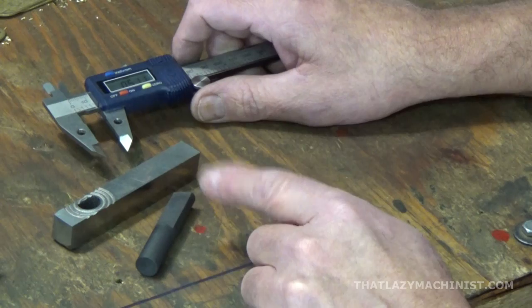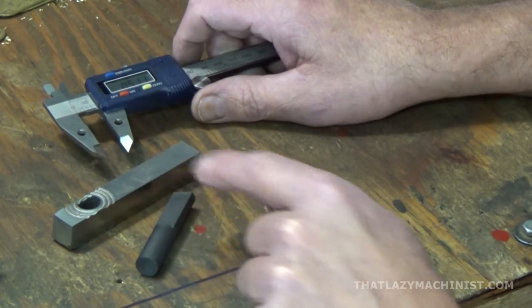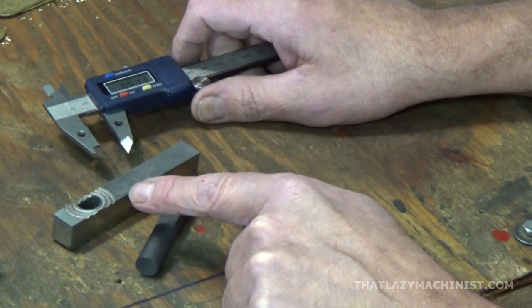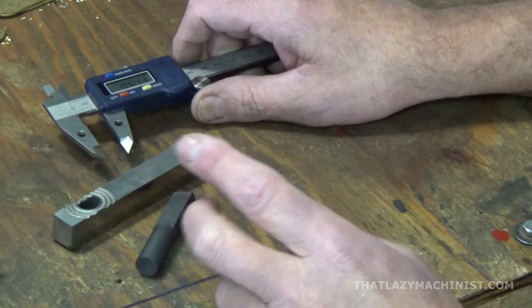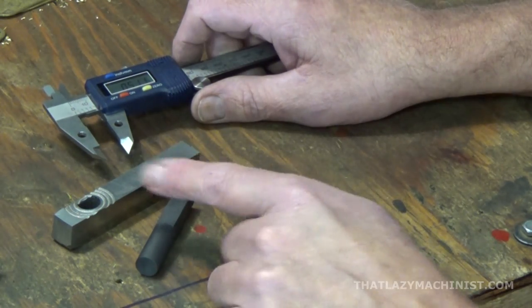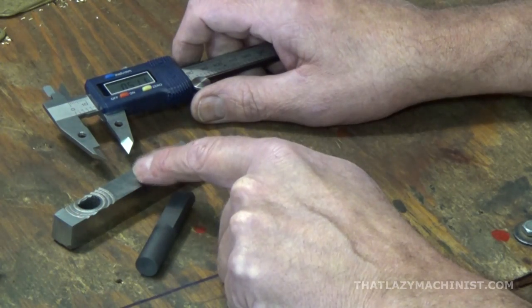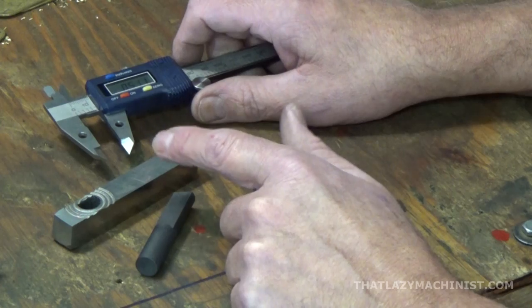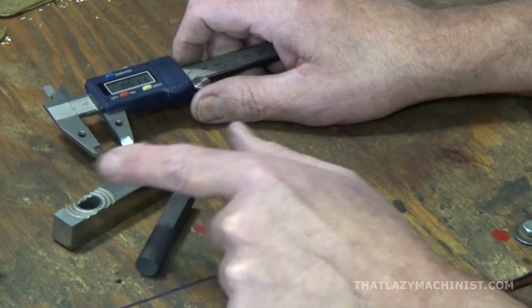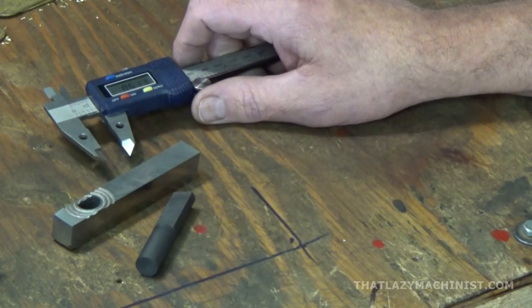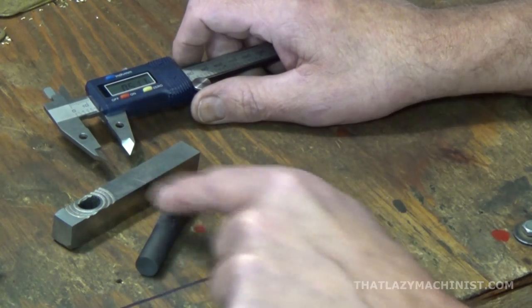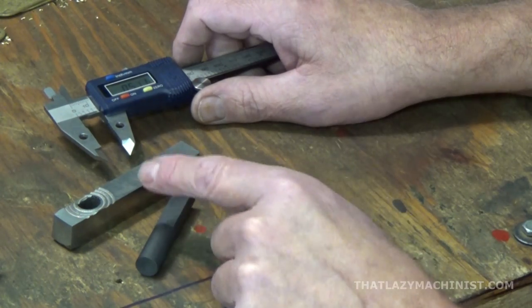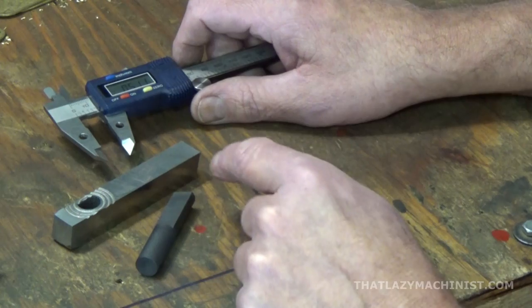It is important to mention, though, that it is very constant. If I cut several holes with the same power of discharge that I was using, I'd always get that same 6.5 thousandths gap. Now, where could that change? If I were cutting a different type of material. Most steels will have about the same gap, but if I were cutting, let's say, a bronze or a brass or a copper, that gap between the electrode and the part would be a lot greater, because that material has a much lower fusion point.